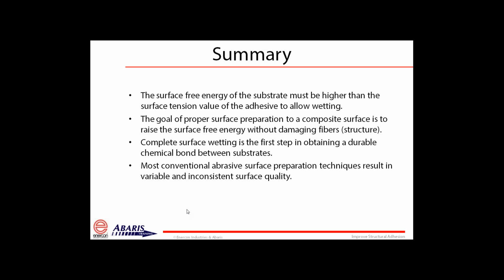Thank you, Ryan. Very good presentation. My summary goes back to the slides that I presented at the beginning, where achieving that raised surface-free energy value of the substrate so that it is higher, preferably much higher than that of the surface tension value of the liquid adhesive or film adhesive, is a necessity to getting that first stage of the chemical bond. Again, the goal of proper surface preparation is to not damage the fibers in a composite structure. And as you can see by the presentation that Ryan did, that can be achieved using the plasma system.